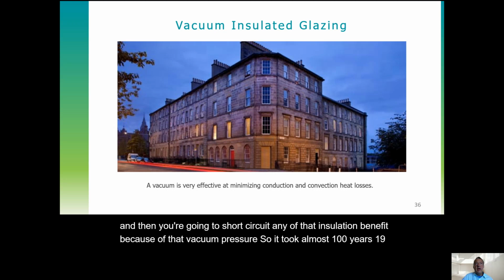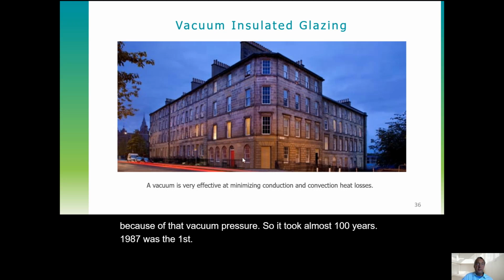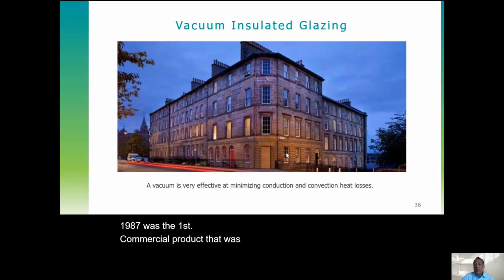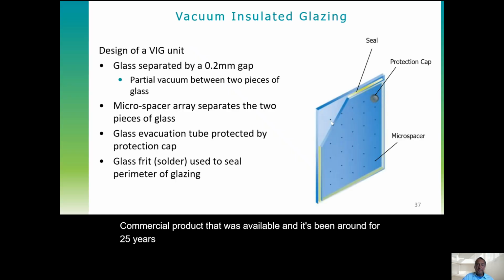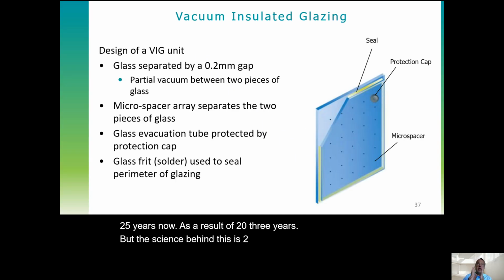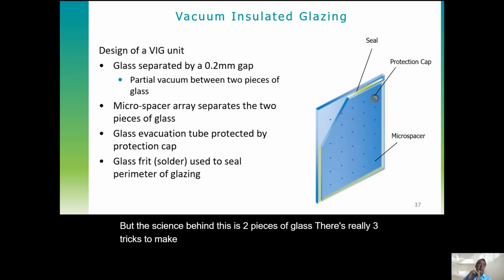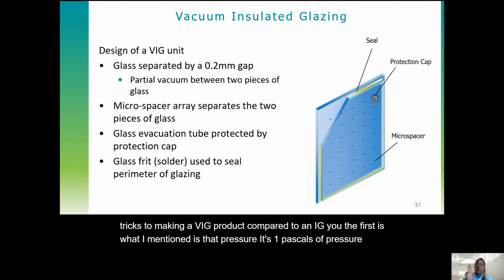1987 was the first commercial product that was available, and it's been around for 25 years now as a result, so 23 years. But the science behind this is, it's two pieces of glass. There's really three tricks to making a VIG product compared to an IGU. The first is what I mentioned, that pressure. It's 0.1 pascals of pressure. That's about 1 ton per square foot.